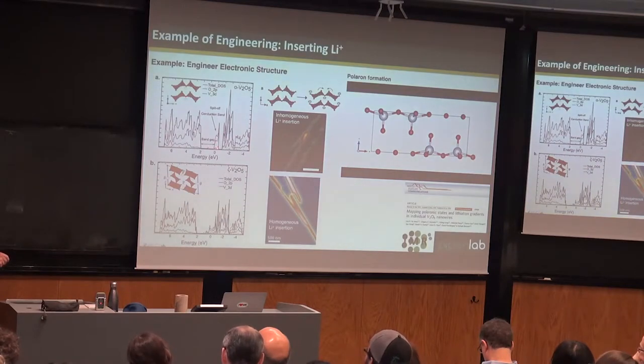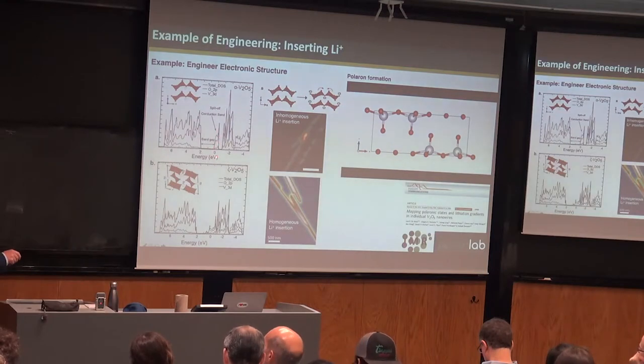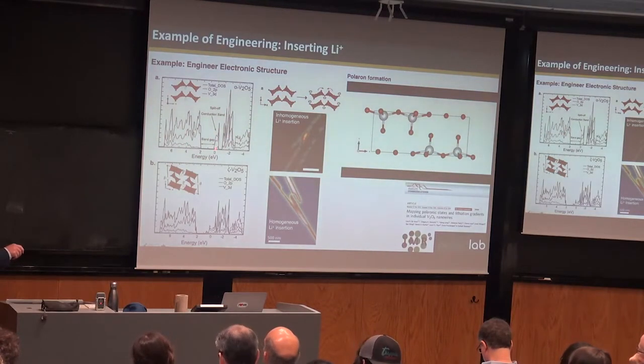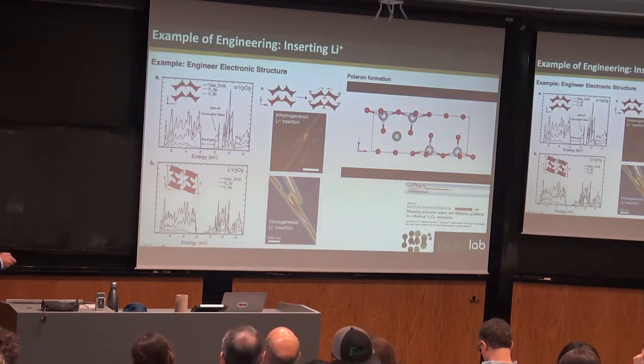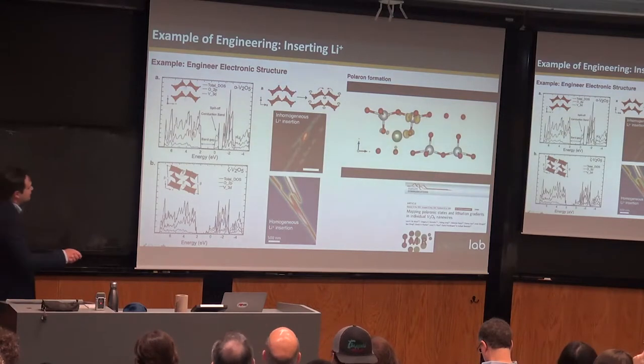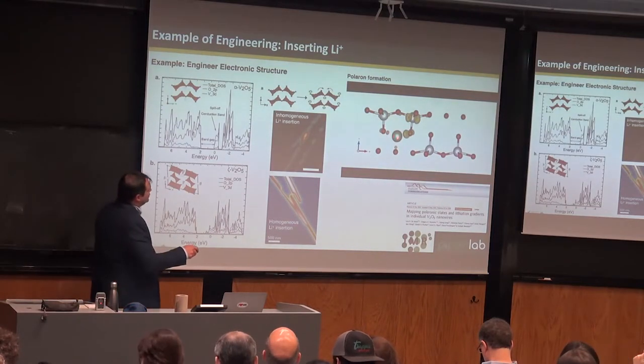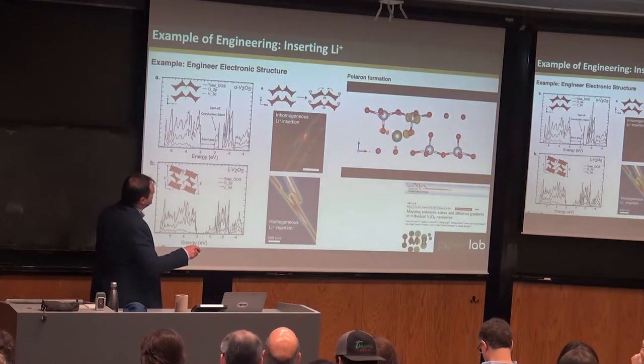In that case, the structure, because of the symmetry and the bonding, essentially you get a split off state. So you get these unoccupied states from the vanadium 3dxy, I believe, split off from the rest of the manifold. And so when you put lithium into your system, it preferentially fills this state. And by doing that, it forms a polaron where the charge is localized spatially and it disrupts the bond angles.